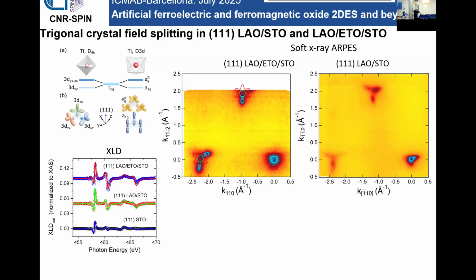And for some reason, in the 111 LaAlO3 it works. But if we go to very large gate, for example in the experiment we are doing now, where we are working at positive gate, for sure we need multiband physics. So your view, if I understand correctly, is that even if the trigonal field is small, if you have multiple bands, the anti-crossings together with the spin-orbit coupling can give rise to this kind of nonlinear transport, but it's okay. I mean, the experiments are like that.